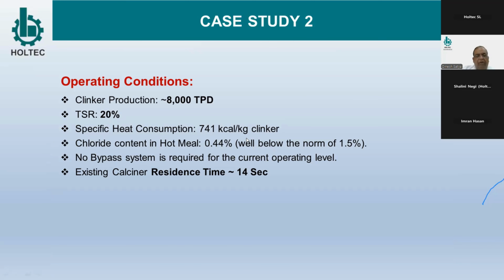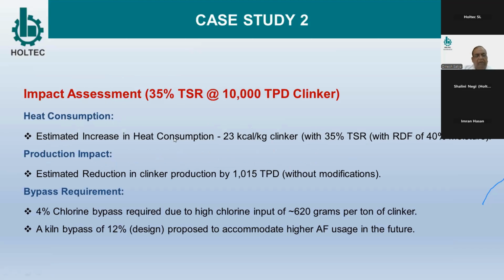Heat consumption was 741, and chloride content in hot meal was 0.44, which was well within range. So no bypass requirement was there. And the calciner was adequately sized, at 14 seconds. From this operating condition, we now had to go for 35% TSR. So we studied the impact. What will be the impact of 35%?